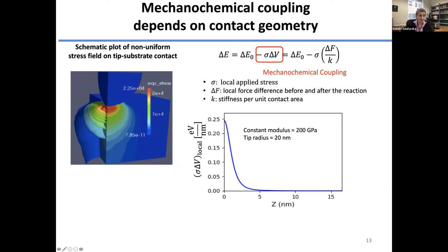coupling component. So we talked about the activation volume, right? And we said the majority of this can come from the bulk, the near interface region. And the other term in this expression is stress. So different contacts, different sizes of contacts, different geometries will have a different stress distribution in the near interfacial region. And therefore, they will contribute differently to this mechanochemical coupling.